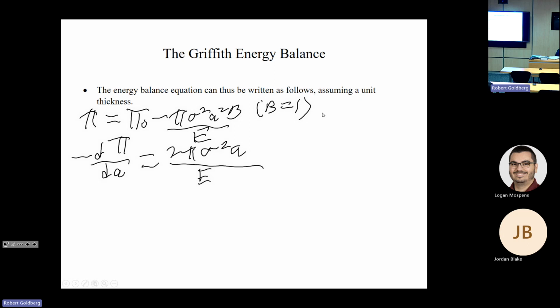And this is just simply, the derivative of A squared is 2A. Everything else is constant. And likewise, we can say that our surface energy term is equal to 4 times A times B, which we're assuming is equal to 1, times the surface energy. So the derivative of our surface energy term with respect to the half crack length is just equal to 4 times the surface energy of the material.